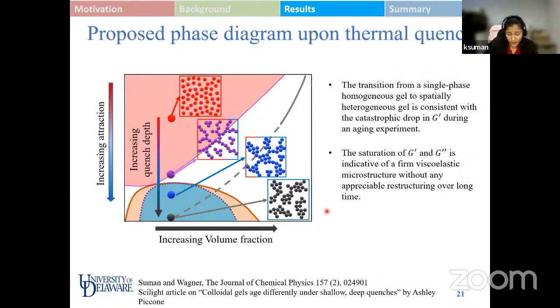The microstructure which causes the changes occurring while changing the temperature is shown by the schematics over here. At 40 degrees, we are in the liquid-like state, where the colloidal particles are very nicely dispersed in the medium, shown by the red spheres in this box. As we decrease the temperature, it enters the gel-like region, where the particles share attractive interaction and form a nice space-spanning percolated network, as shown by the purple schematic over here.